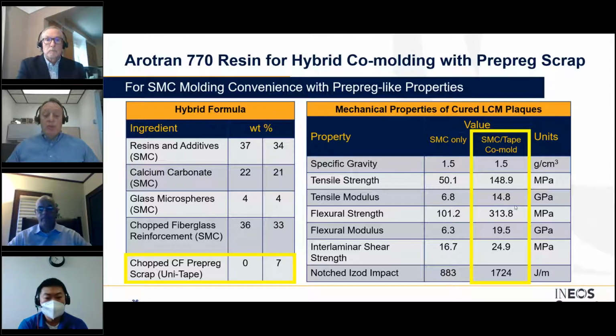The resin found in the unidirectional tape and the SMC are actually chemically compatible and chemically bond to one another during compression molding. And because the continuous fiber fraction added was really quite small, it didn't impact the cosmetic performance or the specific gravity of the finished part. The placement of the unidirectional tape could mimic the potential use of a preform made with prepreg resin. The combination of these two technologies shows how simply to obtain a Class A SMC with mechanical properties of a structural SMC, or, if you will, how to obtain a high-performance structural part with Class A cosmetic properties.